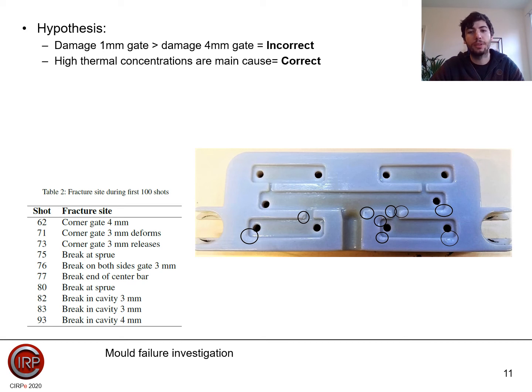Reviewing the occurring damage to the mold material reveals that damage is not correlated to the size of the predefined sections with high shear rates. In fact, opposed to what was hypothesized, the 1 mm gate did not fail within the 100 performed shots. Actually, the occurring high temperature concentrations are the main cause of the early failure in the mold in these gates, which is most probably due to a combination of thermal expansion and degradation of the digital ABS material.